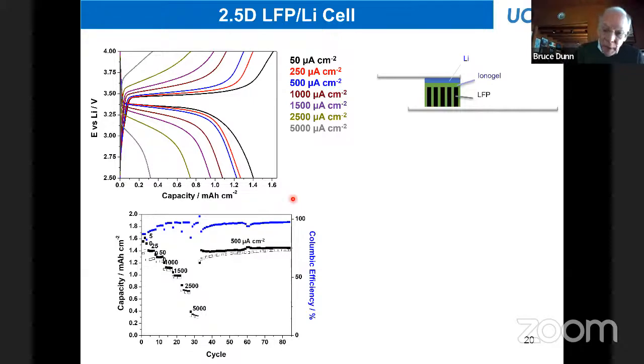And these are our results. This is now for lithium iron phosphate rods, an ionogel electrolyte, and a lithium top electrode. You can see we have a characteristic curve that we normally get for lithium iron phosphate. What's nice about this is that the theoretical value of the areal capacity is indeed 1.5 instead of 1.4. So at 50 microamps per square centimeter, we just about get theoretical. But what I'm most pleased at is being able to operate at a milliamp per square centimeter and you are only down by about 30%.